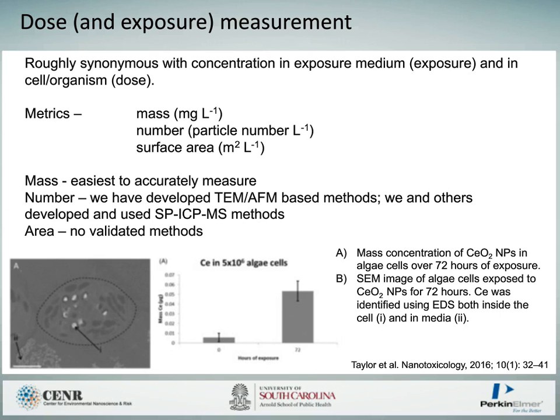And on the same slide, you can see data from a publication of ours where we looked at dose, or at least concentration within cells, by a TEM method. And that's a useful method. And it gave us some invaluable data. But it was time consuming. It's only semi-quantitative. And there are other developments which need to be performed. And so the ICP-MS becomes an invaluable additional tool.